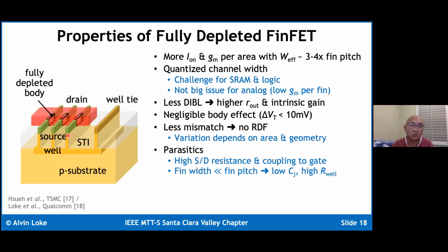One other thing to note is that the fin width here is much less than the fin pitch. Typically, they're about 20 to 25% of the fin pitch, which means that although the junction capacitance facing downwards is a lot less because you have a lot less area, your well resistance is also a lot higher. And as we'll see later, this has significant implications on things like latch up, where you need very low well access resistance to mitigate.